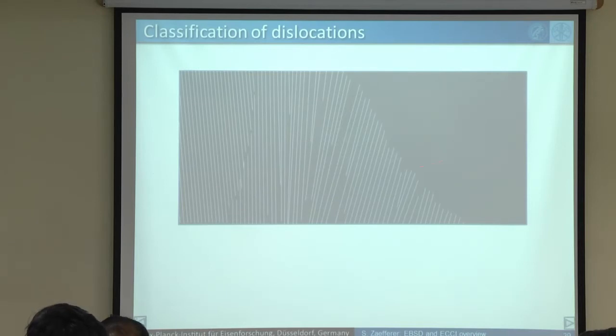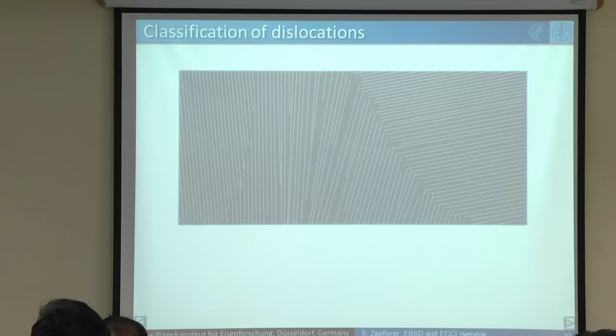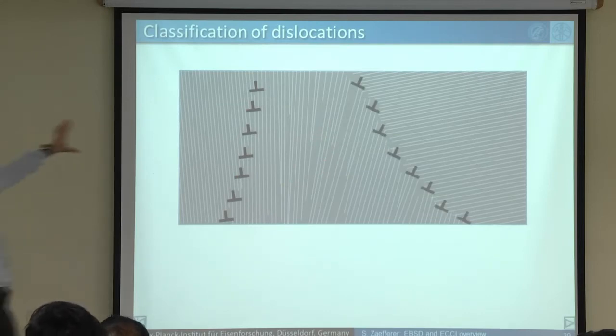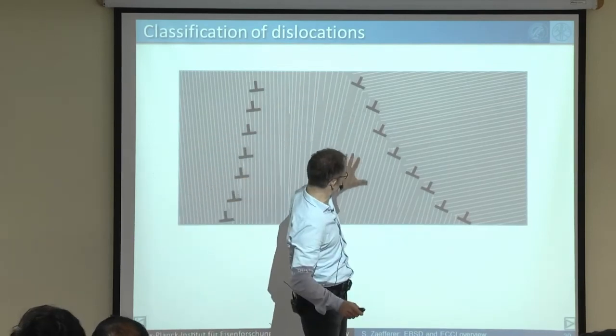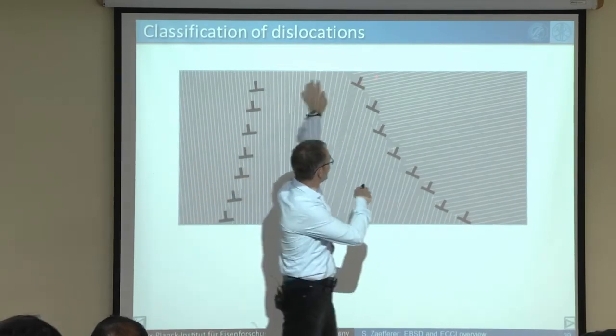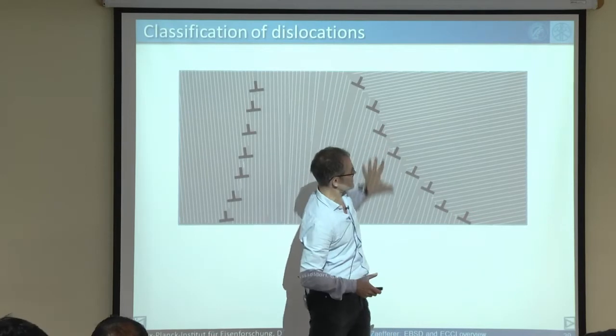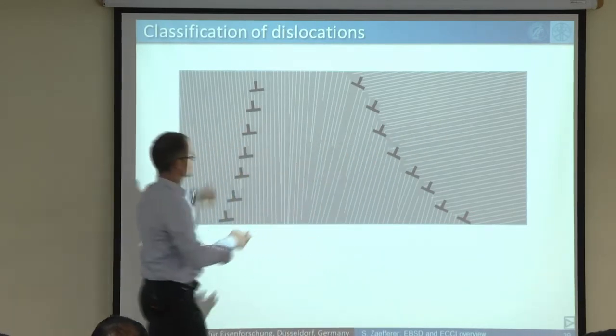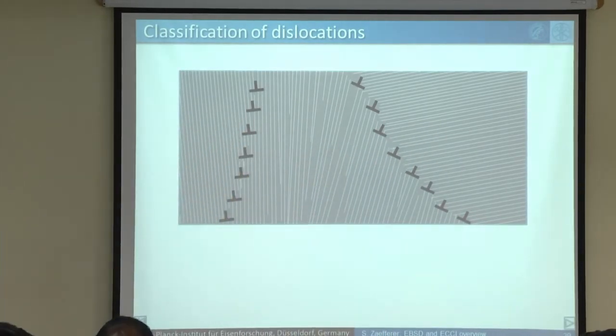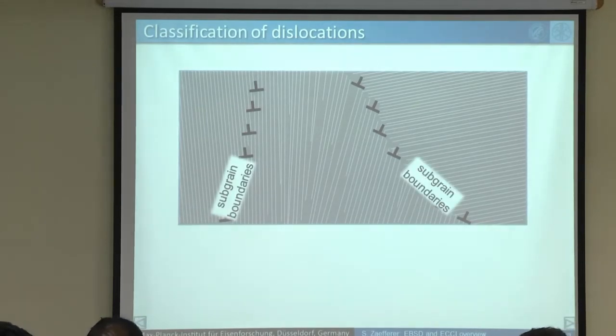Imagine you have a lattice like that, and this lattice is connected to another lattice like that, and another lattice like that. And now we plot the dislocations inside which make the misorientation from this crystal to this crystal and to this crystal here. It's a bad drawing. In principle, this should be almost close to this one here. There should be a small angle grain boundary in between, and these dislocations make just a transition from one orientation to the other. These dislocations are forming subgrain boundaries.